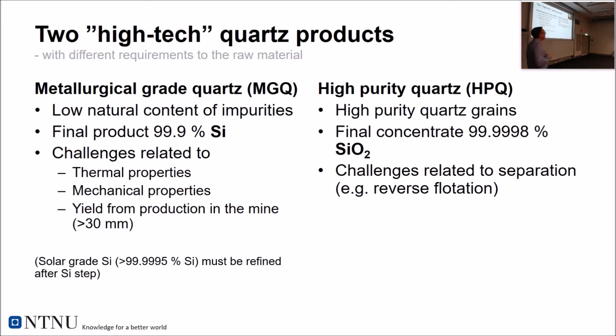the silicon they produce from these furnaces is intended for chemical use and as a raw material to electronic grade, that is further refinement of the silicon, or it can be for solar grade, which you in Brisbane can see as the solar panel on houses and commercial buildings. That is a lot of talk about in the news and media for the moment, I've seen. Solar grade silicon is 99.9995 at least percent silicon, and this refinement has to be taken in the second step, so it's more than 50%.